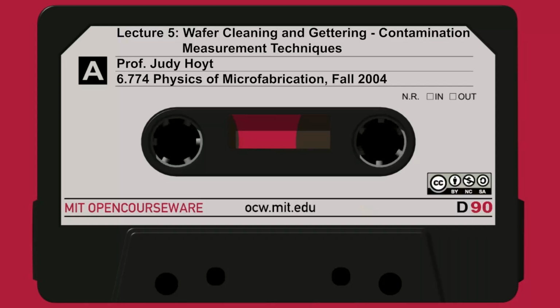So basically, from looking at these capacitance voltage measurements, we can extract a lot of quantitative information. In fact, we can get the oxide thickness. Remember, we had C-ox. C-ox just depends on the dielectric constant and the oxide thickness. So once I get that number, I know the area, I can calculate the oxide thickness. I can get the substrate doping from the depletion capacitance. And you can get all these different interface charges, Q_F, Q_IT, the mobile, and the oxide trap charge. All those, just by doing CV measurements in their different configurations and frequencies, we can get this information, which tells you about the electrical quality of the device.